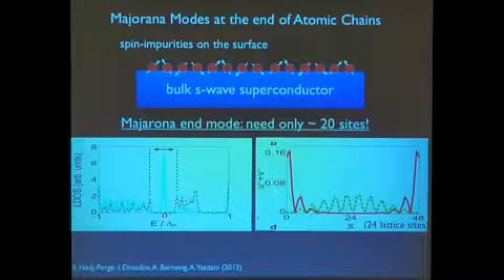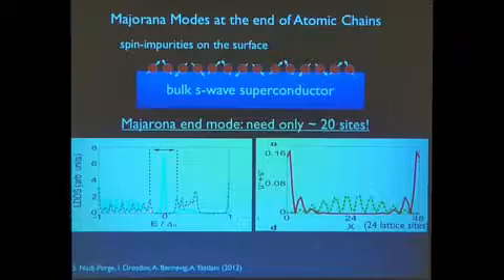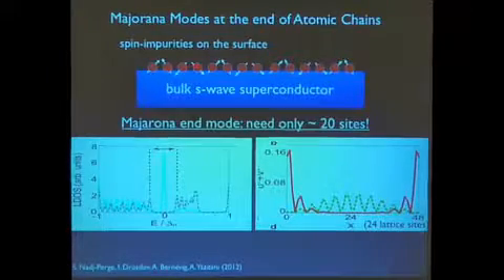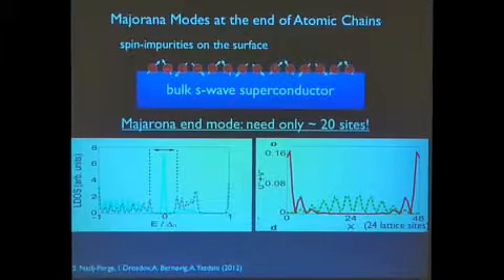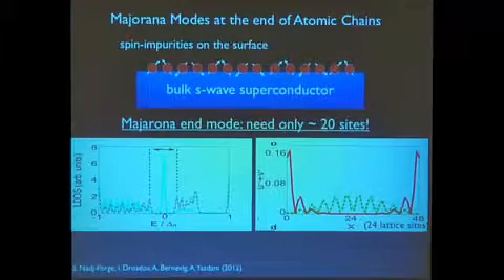What you're looking at is a state that lives right at the edge of the wire with only 20 sites. And very clearly inside there is some sort of a gap, which has to do with an induced P-wave gap on this wire, which I won't go into the details of, but you can see that there is a very nice zero bias peak coming from the calculation.